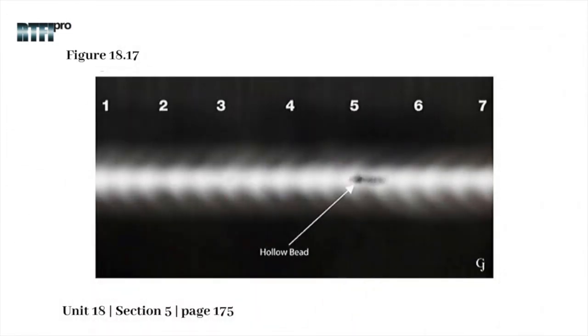Hollow bead is found in the root and will have a linear appearance. If there is no acceptance criteria mentioned for hollow bead, it shall be evaluated as an elongated indication if satisfying the requirements of an elongated indication.